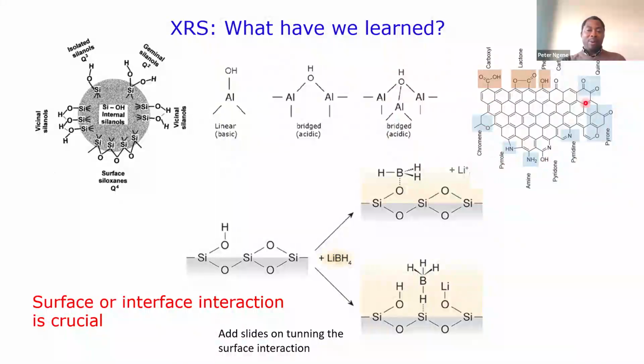If you also look at carbon, the same thing. Carbon is always covered with a lot of surface groups. So even for the carbon that we used before, those BO-like bonds that we saw would just be interaction between the LiBH4 and this surface group, leading to something at the interface that looked like boron-oxygen, which means that our sample was not completely oxidized as we thought in those days. It's just the fact that our active material interacts with these surface groups to give us the X-ray pattern that we saw.